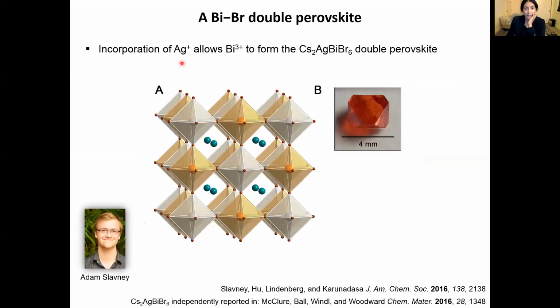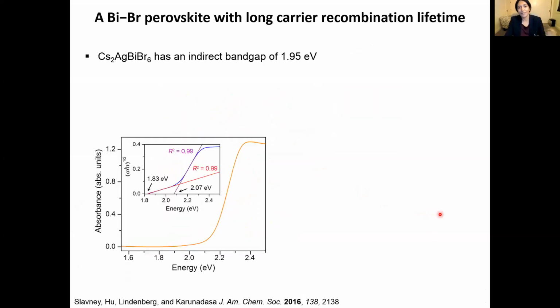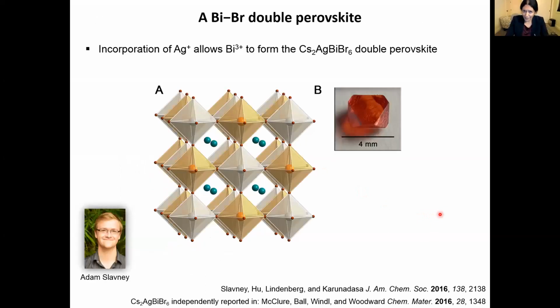Adam found that silver and bismuth goes into a double perovskite, and he was able to form these glorious crystals where the morphology of the crystal reflects the cubic symmetry of the lattice. And we decided to evaluate this material as a solar absorber. So first thing to note is it's red. It's not black, as a solar absorber should be, so the band gap is probably too high.